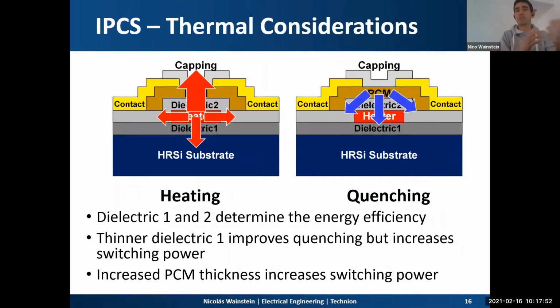Certainly, during the actuation, some of the heat is dissipated through the dielectric 1, 2, and the contacts. Therefore, proper engineering of the different layers is required to achieve switching at all and low switching power. Recall that the cooling must be fast. We need a fast quenching process, so the dielectric 1 must be kept as thin as possible. And also, the more the contacts overlap the heater here, the larger the energy dissipation will be. This poses a very interesting thermoelectric trade-off between the thickness of the different layers.